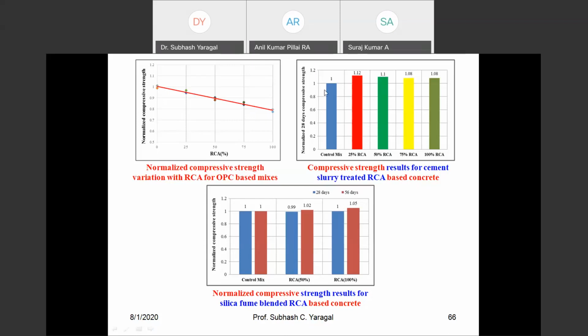So if you do that, your control strength is here. For 25%, we have got 12% more than what is for the control mix. So these RCA, recycled coarse aggregates, have been treated with cement slurry. So whatever your replacement, you have strengths more than what is for your virgin aggregate. So you can definitely go for full replacement of your virgin coarse aggregate by recycled coarse aggregate if you are treating your RCA for about 24 hours with 5 to 10% of cement slurry. So you lose around 5 to 10%, but you get the efficient aggregate so that you get the strength equal to what is for the normal concrete.